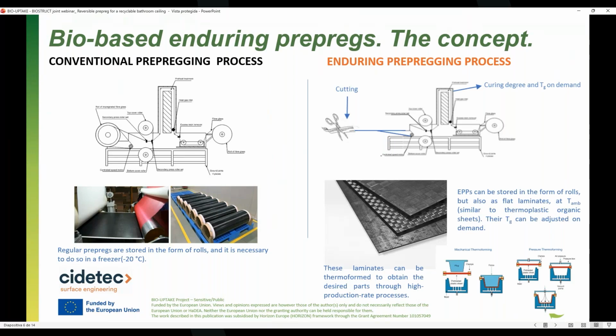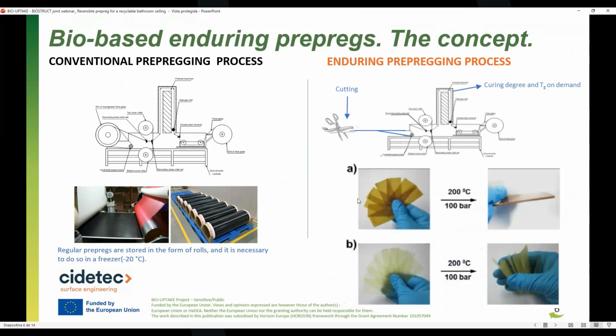So we can store them at a Tg that can be adjusted on demand, and these laminates or rolls can be used at room temperature and thermoformed to obtain the desired parts through pressure molding. So if we apply pressure and temperature to semi-cured prepregs, or to these enduring prepregs, we obtain a multi-layer